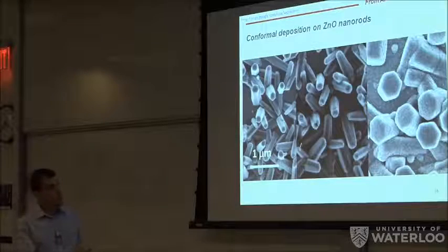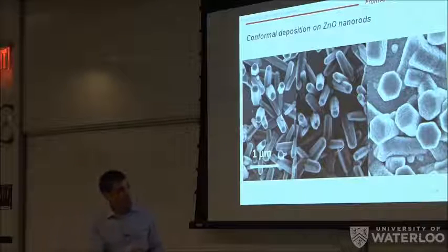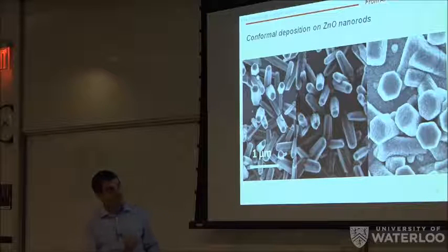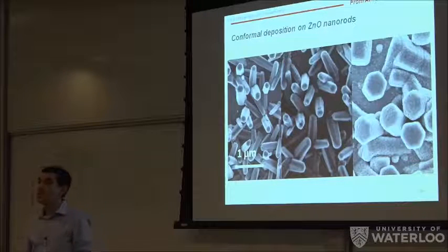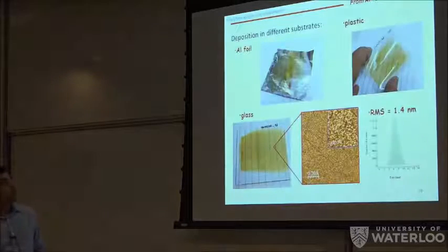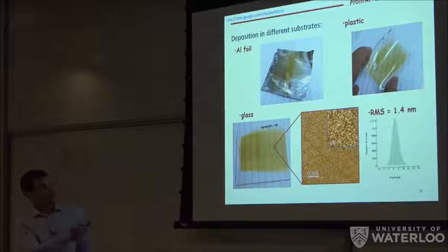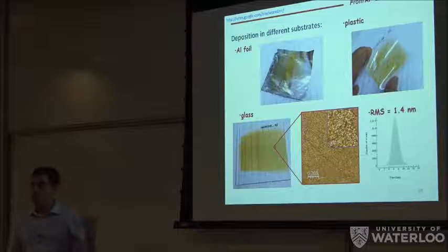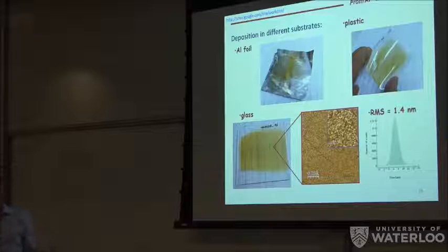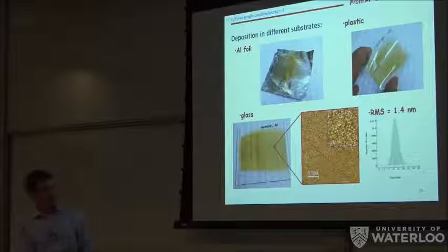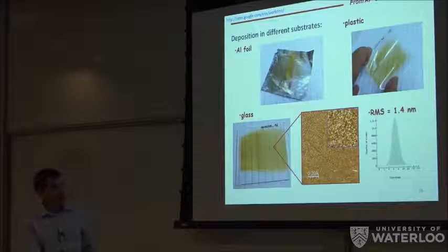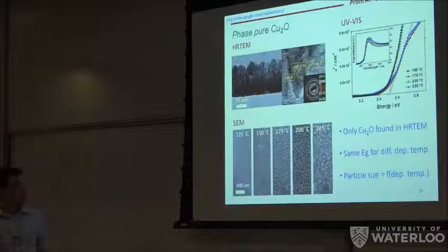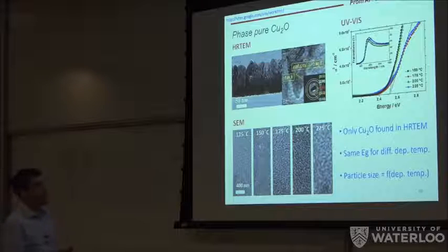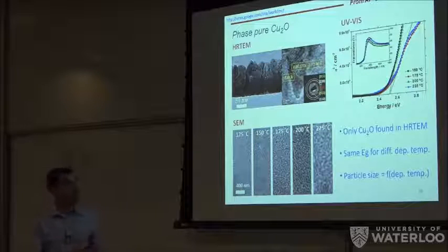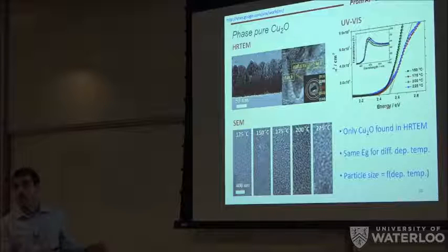And again, we tried to coat nanorods with our spatial atomic layer deposition system. And you can see, again, it's very conformal, very neatly coated. And again, you can deposit on different substrates, metal, plastic, because we could do it even at 125 degrees. And again, the films are nice, homogeneous, crack-free, quite smooth. So very nice. When we checked the structure, it was pure cuprous oxide to the TEM, no metallic copper, no copper oxide.